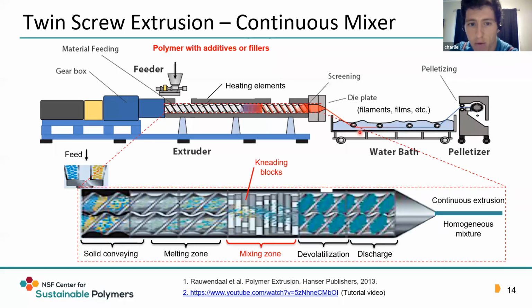Now we'll take a more zoomed in look at what goes on in the mixing section. In the twin screw, you have two screws. You have a conveying zone and a melting zone, and then a mixing zone. The mixing zone is where you see those kneading blocks, which you saw earlier in the beyond the classroom figure. In these kneading blocks, this is where the mixing mostly occurs. You'll have both shear and extensional flow, and it is very complex. You also then have a degassing zone, and then the material is discharged and extruded into parts.